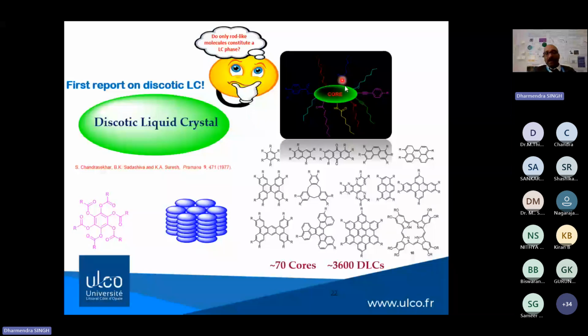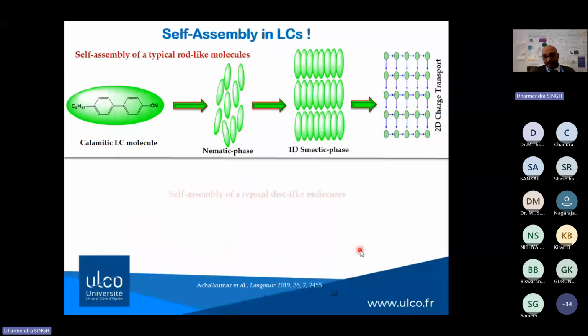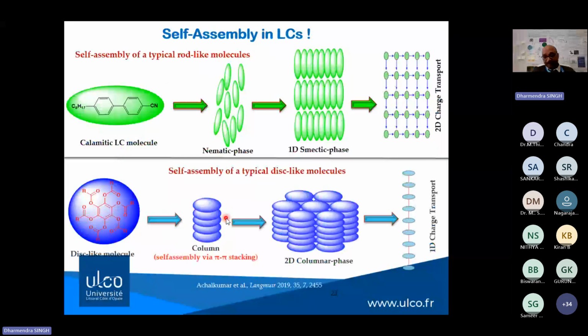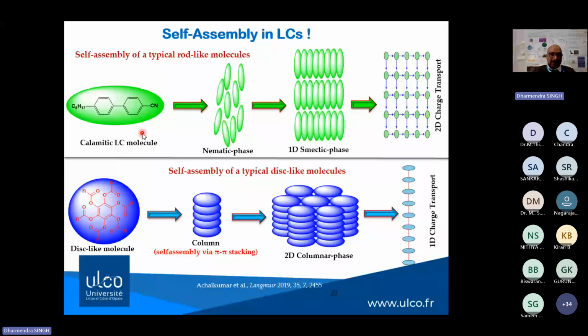Okay, and this central core will be covered with peripheral alkyl chains or some functional group depending on the condition. You could see here, thanks to the chemists who have developed more than 70 cores, the different cores, and depending on these cores, more than 3600 disc-like columnar materials have been developed and investigated by the physicists. So why are these materials very important? Because these materials are self-assembled. Self-assembled means they can self-organize in any matrix.